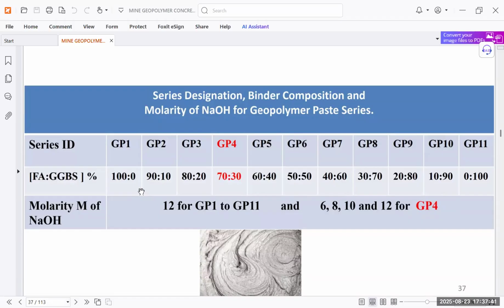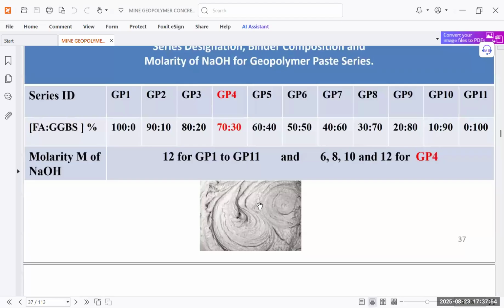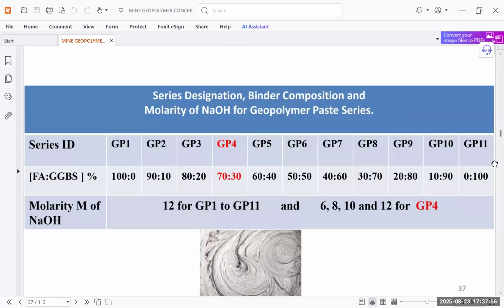So you can see in geopolymer concrete 4, the fly ash to GGBS ratio is 70 to 30. In this, molarity of 6, 8, 10, 12 is taken. And the molarity of NaOH is 12 for GP1 to GP11. These are the different ratios that will meet the different requirements of the geopolymer concrete that will be used at the site.